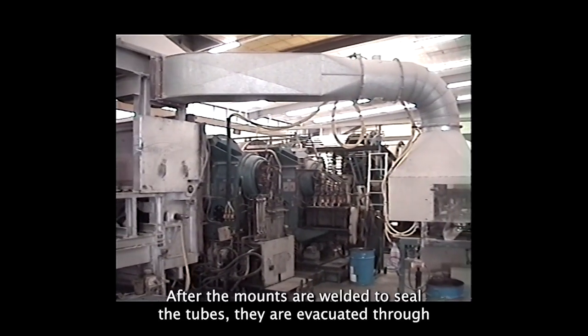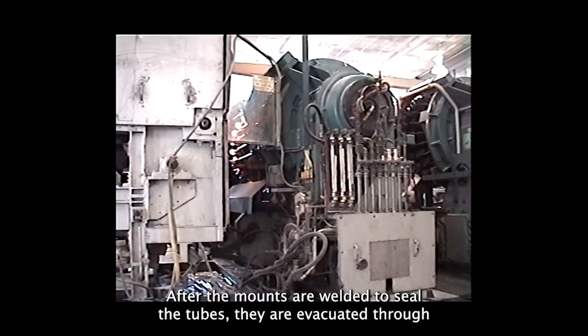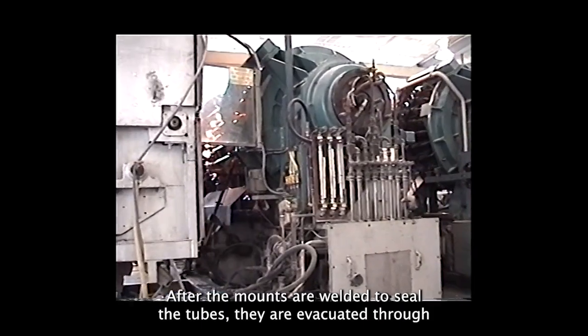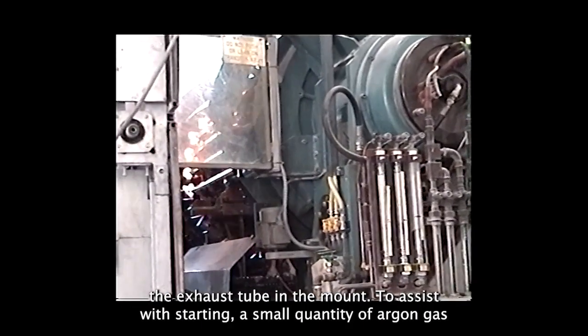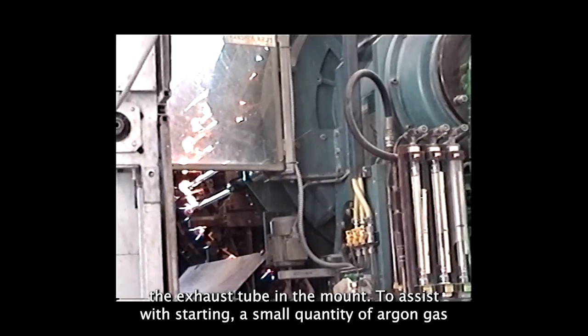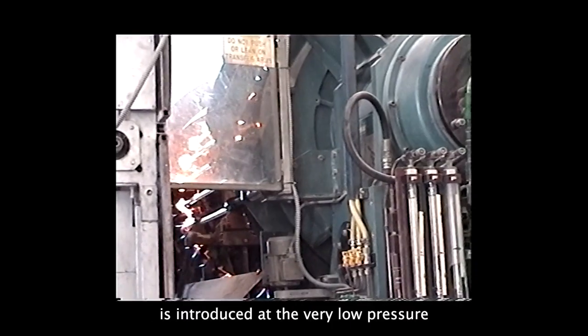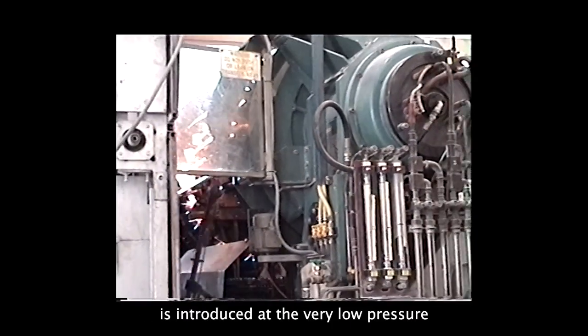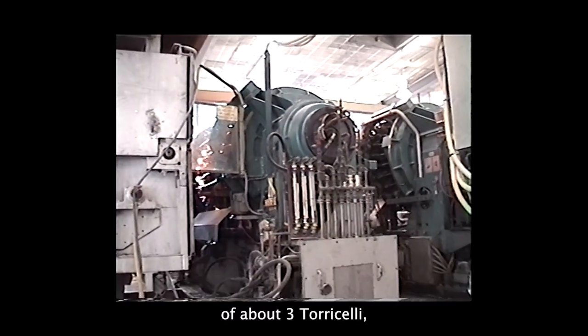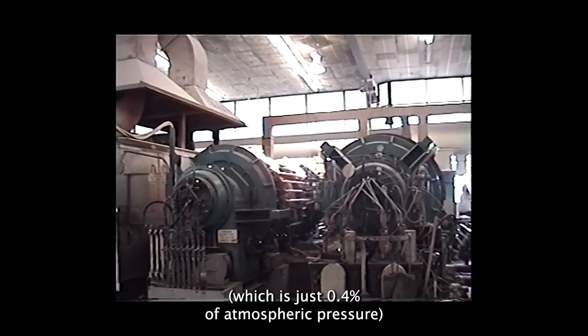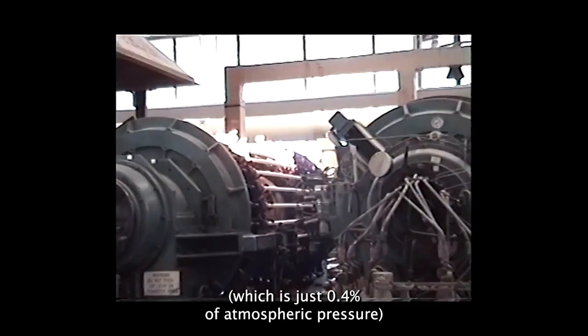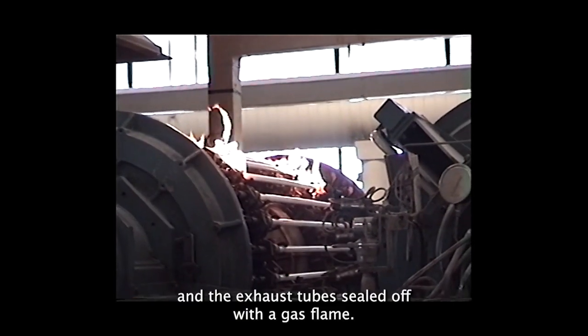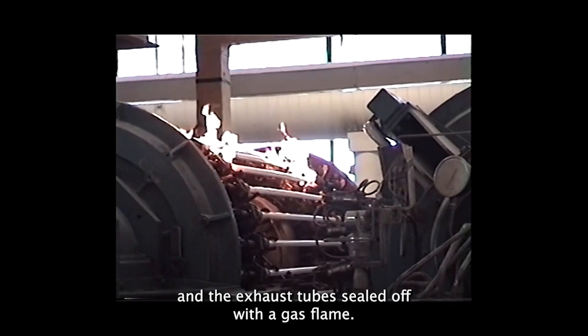After the mounts are welded to seal the tubes, they are evacuated through the exhaust tube in the mount. To assist with starting, a small quantity of argon gas is introduced at the very low pressure of about 3 torricelli, which is just 0.4% of atmospheric pressure, and the exhaust tube sealed off with a gas flame.